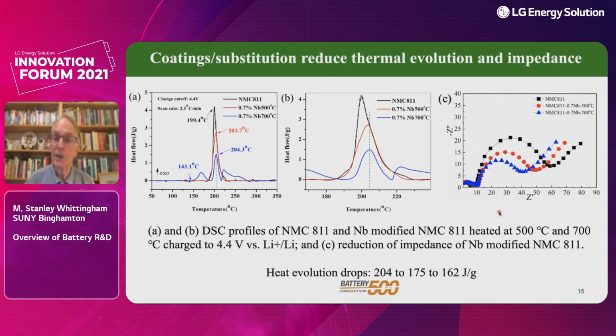But the other key feature here, the impedance of the modified materials, is much lower than the unmodified. So here's the black one, unmodified, surface coated, substituted. Again, we're modifying that surface so it's not so reactive. We reduced its resistance.